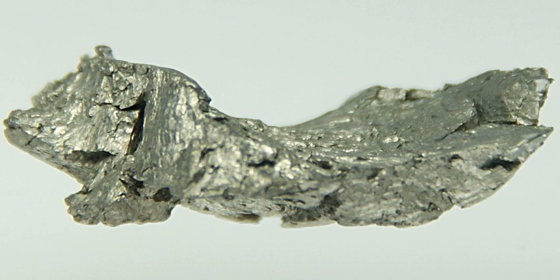Production. Gadolinium is produced both from monazite and bastnasite. Crushed minerals are extracted with hydrochloric acid or sulfuric acid, which converts the insoluble oxides into soluble chlorides or sulfates. The acidic filtrates are partially neutralized with caustic soda to pH 3 to 4. Thorium precipitates as its hydroxide, and is then removed.